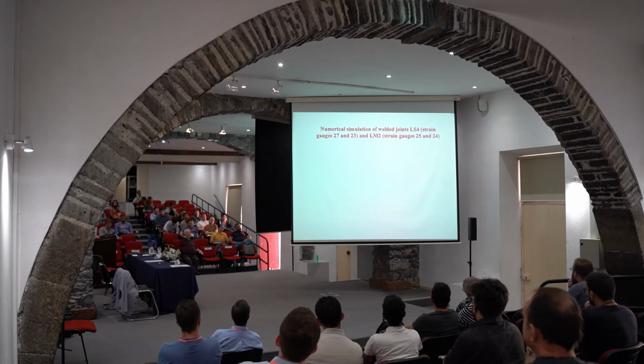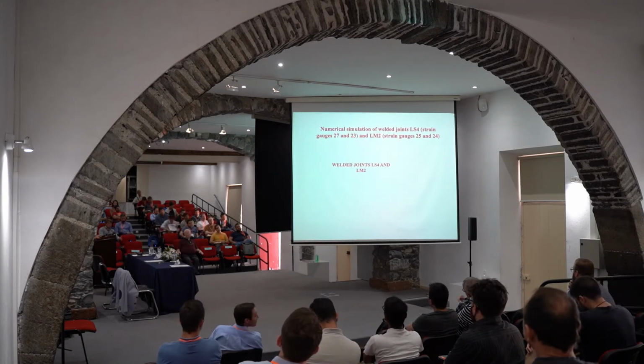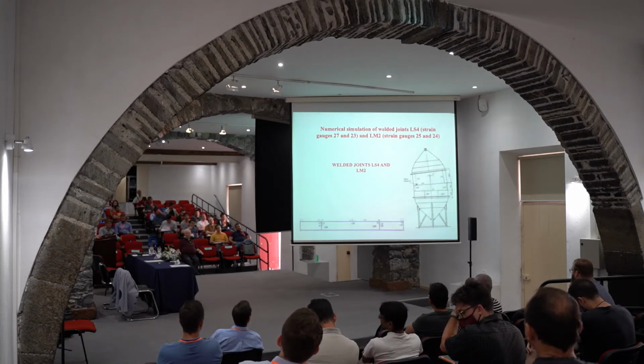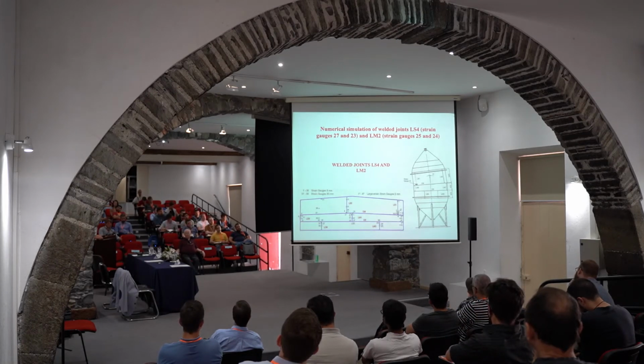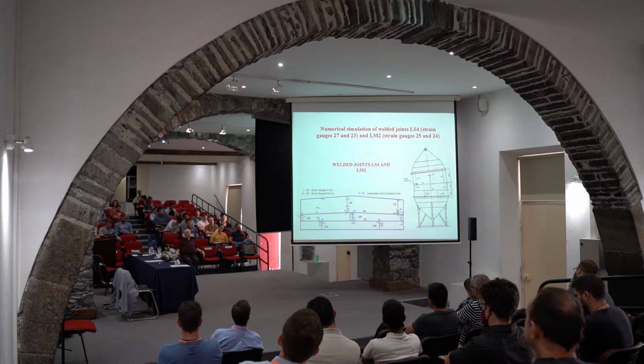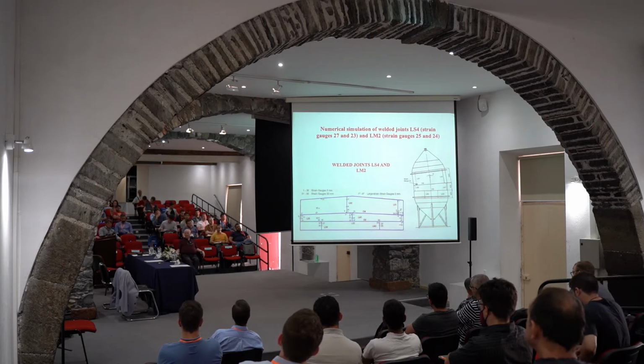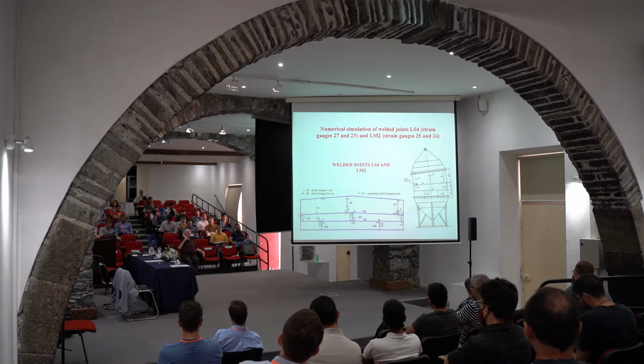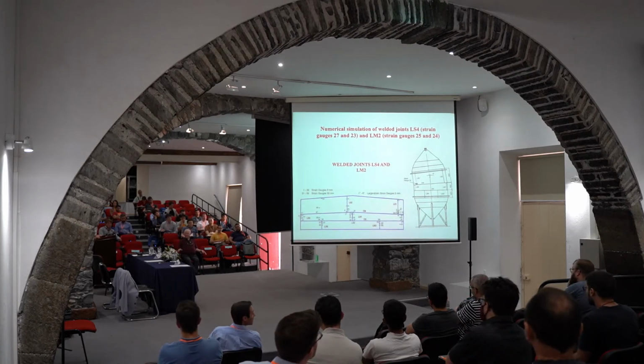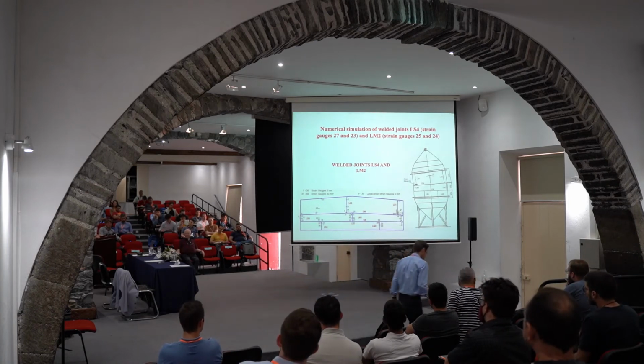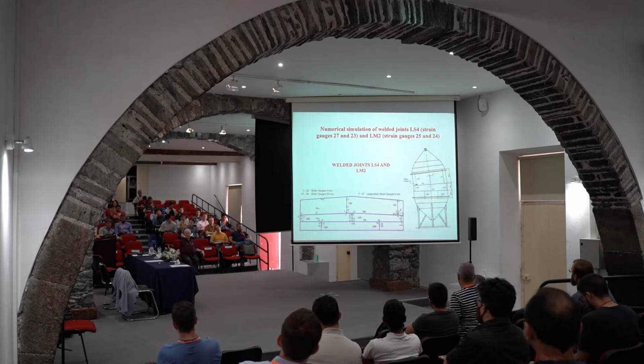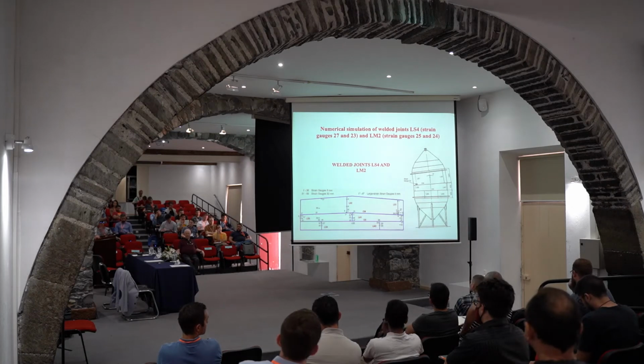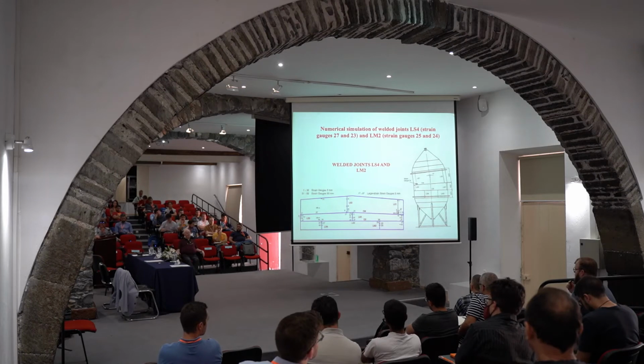And we, as I told you, did get this plastic strain at the end. Of course, the point is that according to theory, we should not have had any plastic strains. But once again, due to stress concentration and mismatching, we actually did get plastic strain. This is one very important and a bit worrying factor. But the other most important factor and conclusion was that this prototype still behaved well from the structural integrity point of view. Those artificial cracks did not start to grow. So even under very high loading and cracks with relatively large dimensions, it was safe.